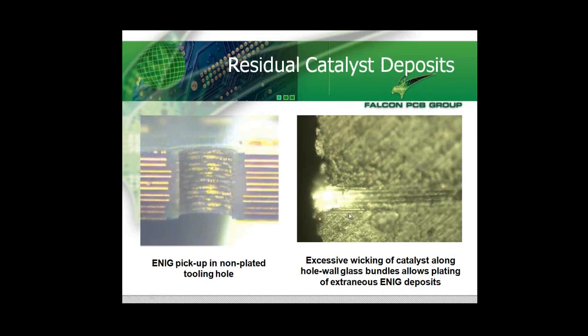On the right-hand side picture, you will see the actual wicking of the catalyst which hasn't been removed, and subsequently, of course, nickel and gold will deposit on top of it. And if you look at the photograph on the left-hand side, you will notice that the microsection, as you see through there, the half hole, you can see a lot of the glass bundles have actually picked up nickel and gold. This should be non-plated through as a tooling hole.